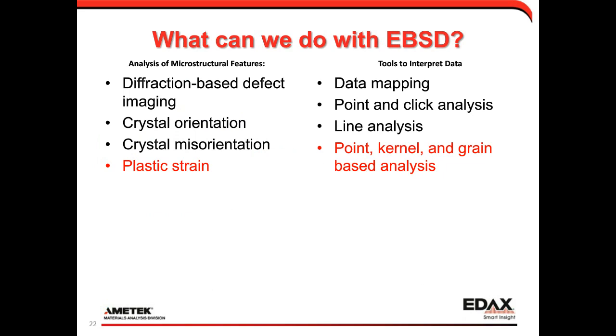Once we're measuring those small misorientations within a grain, we can start to think about quantifying plastic strain measurement. Plastic strain is what happens when we permanently deform a material past the elastic limit. And so we start to introduce dislocations that cause small lattice changes of misorientation. We can measure that with EBSD, and we can do it with a point, kernel, or grain-based analysis.